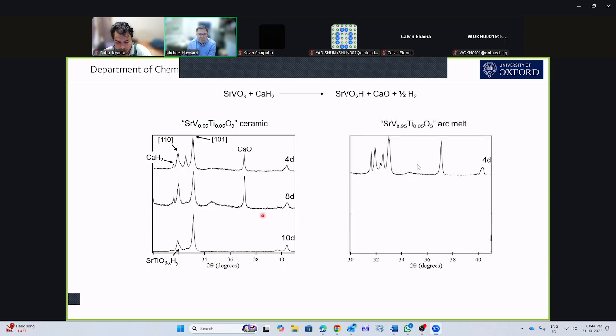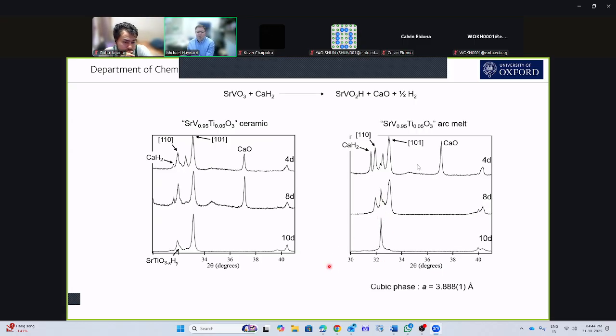If I now do the same for the arc melted sample, after 4 days, again, I've got calcium hydride and calcium oxide. Here's my tetragonal SrVO2H doped with titanium. And then here's my oxygen deficient phase. And then I've got this unknown material here. And as we progress, that unknown material grows until it's the only product at the end. So we end up with a cubic material here rather than tetragonal SrVO2H. So what's this cubic material?